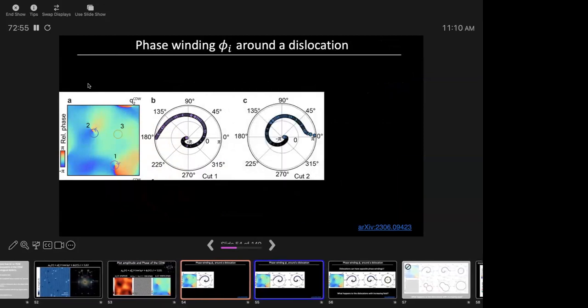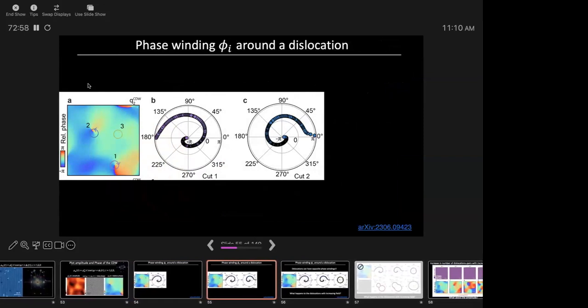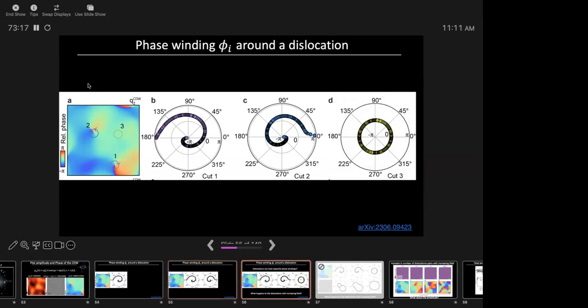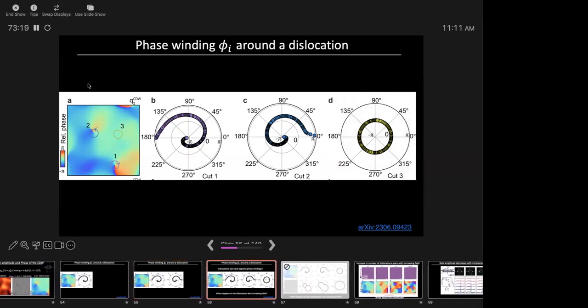Now let's pick another one. So this is this one, and this is the other one. Now, if you pick this one, it goes in the opposite direction. So I've shown you two things. One, you have these dislocations in the CDW. And the second is you can have dislocations with opposite phase winding. And just as a comparison, if you go somewhere else where there's no dislocation, the phase just doesn't change as a function of angle.